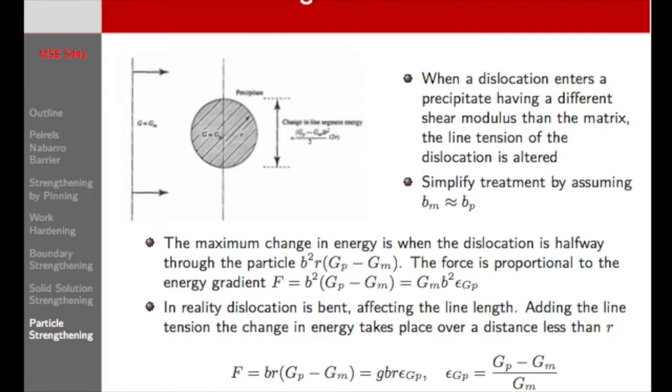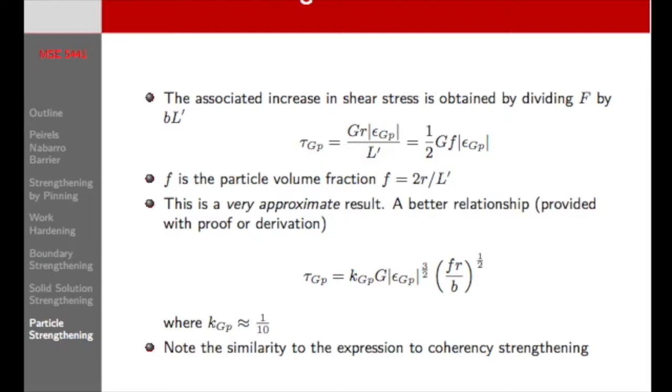There's a modulus effect in solid solution strengthening, and there's a modulus effect in precipitation hardening, and they're both the same thing. The stiffness, the elastic properties of the local environment, are going to affect the energy of the dislocation. It's whether it's just the elastic field around an individual atom, the interaction of the elastic field of the dislocation with the atom, or the interaction of the elastic field of the dislocation with an entire particle of the same material. But it's the same effect.